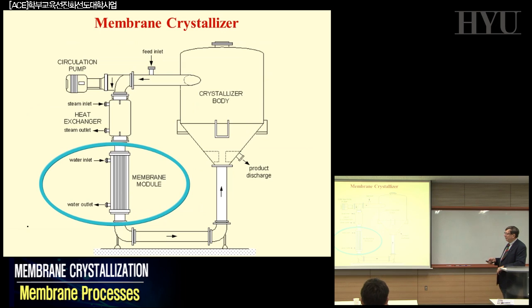So what you have to do, if you have your membrane module, you will try to create a supersaturated solution in the module itself. So you induce nucleation, which is the first step, as when a child is born. The first second is just very important. The same is here, but the real growing of the crystals will take place in another part of the system, another body, where you can also form the crystals and continuously remove them, so that they will not go back on the membrane surface and will not plug the system.